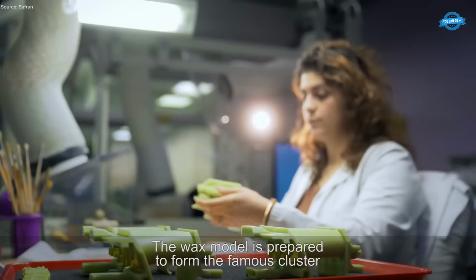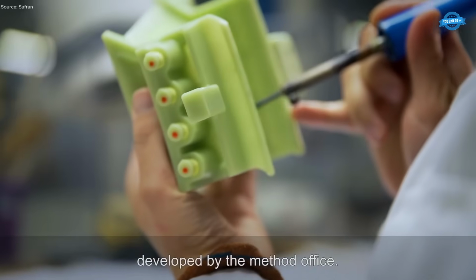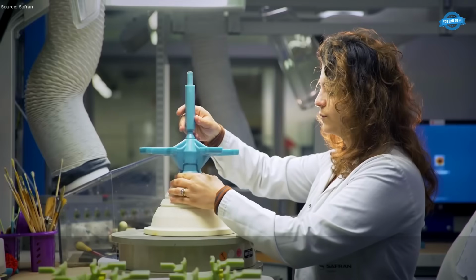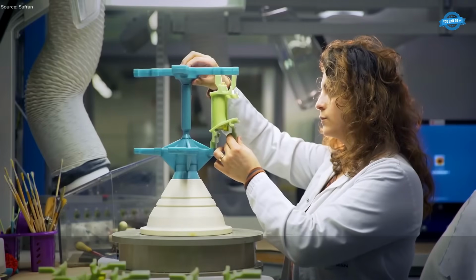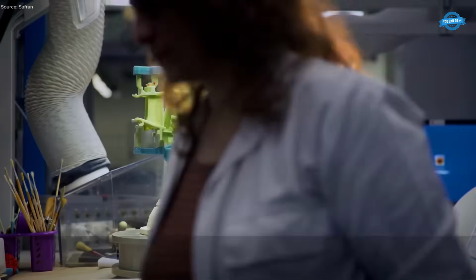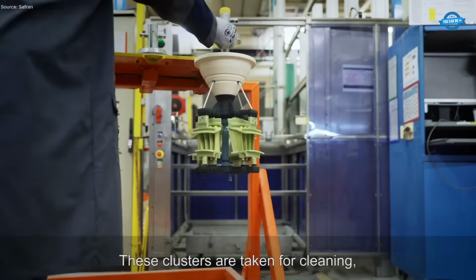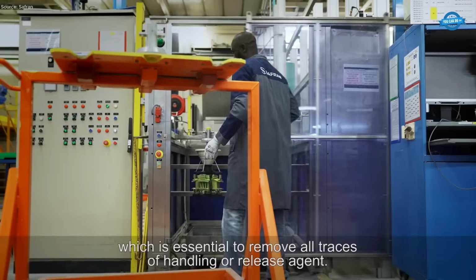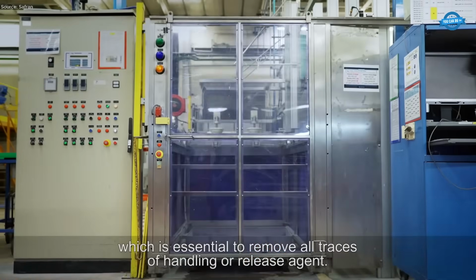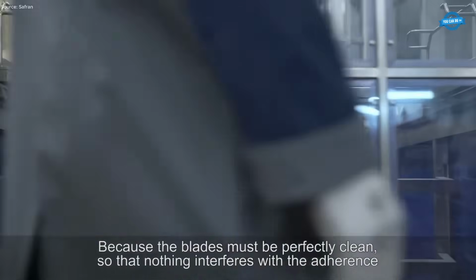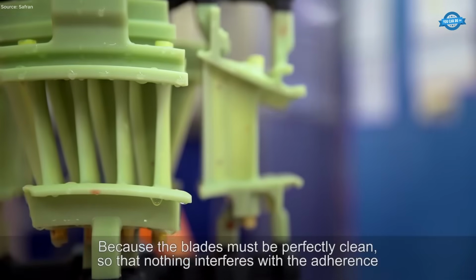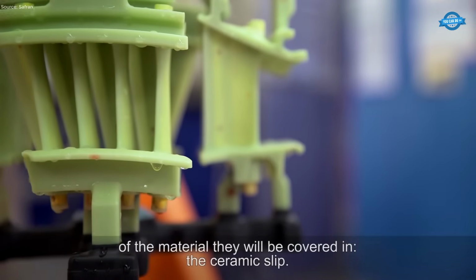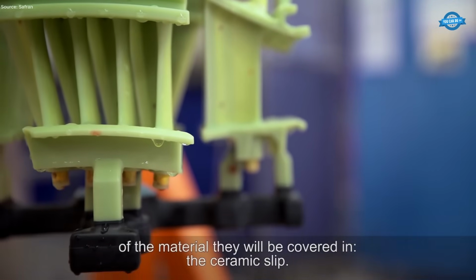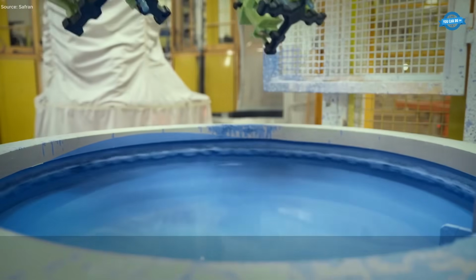Clusters of wax blades are then repeatedly dipped in ceramic slurry and coated with fine and coarse sand. Between each of the 7 to 9 layers, controlled drying times ensure adhesion and shell integrity. This meticulous multi-layer process produces a shell strong enough to endure molten metal at more than 1500 degrees Celsius. The wax is removed in autoclaves under pressure to prevent cracking, and the empty shells are further baked to harden and remove residual wax.